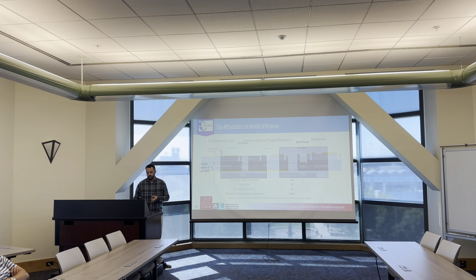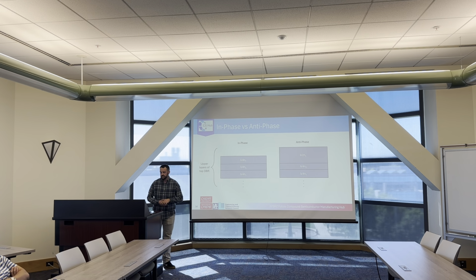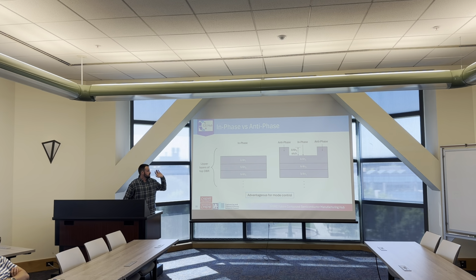So I just want to explain a bit more what I meant about in-phase, anti-phase. So looking at the top layers of the top DBR, an in-phase structure would be where all the layer thicknesses are quarter wavelength, quarter material wavelength. In an anti-phase structure, the final layer is grown as a half wavelength thickness. So then what you do is etch a quarter wavelength thickness, and you have regions where you have anti-phase reflections and in-phase reflections. So this is used for mode control. In terms of the QuickSEL though, we're just making everything in phase, then performing the same test, characterization and analysis.